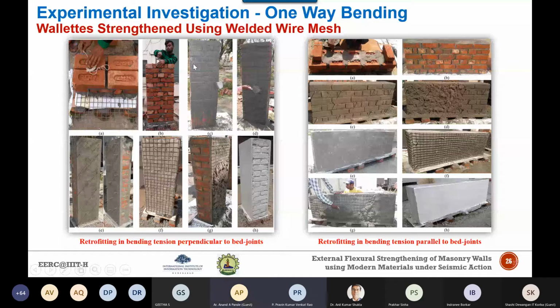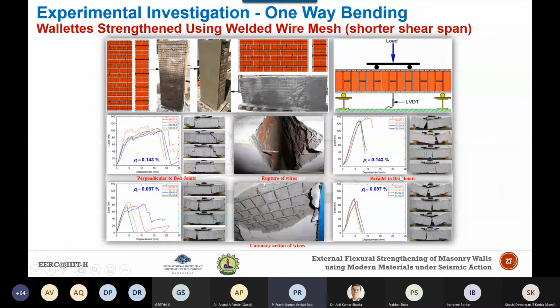Now, if you see the test results, we have tested different types of specimens with varying reinforcement ratio. Here you can see that for bending tension perpendicular to bed joints, they have either failed in sliding shear along the bed joint, or due to diagonal shear cracks, which are basically joining the support and the loading line. Whereas for some of these specimens which are strengthened with 50 mm wire mesh, mostly the failure is associated with flexure, and in some cases sliding shear also took place.